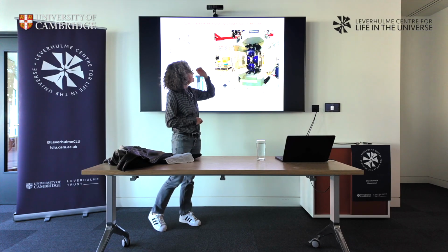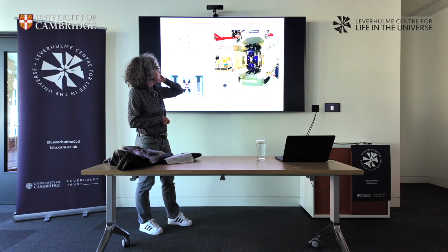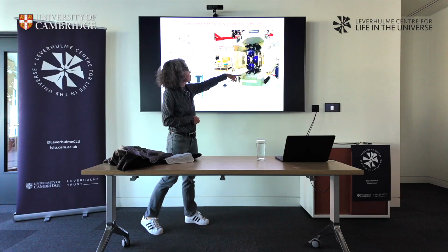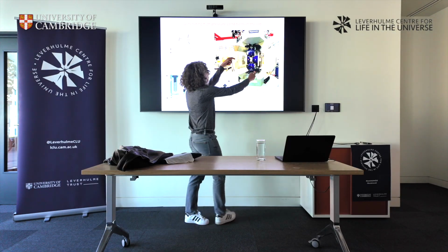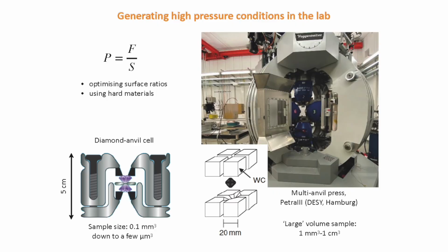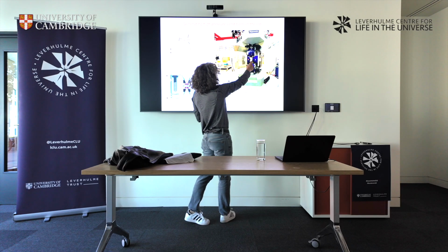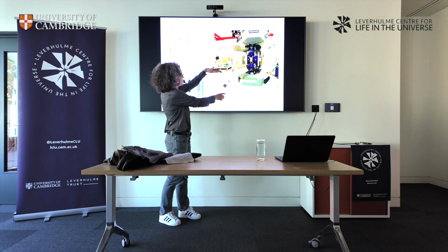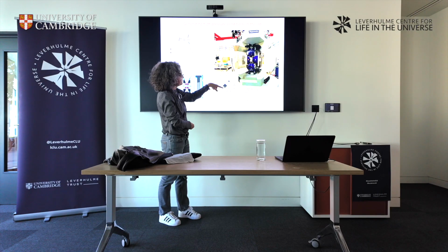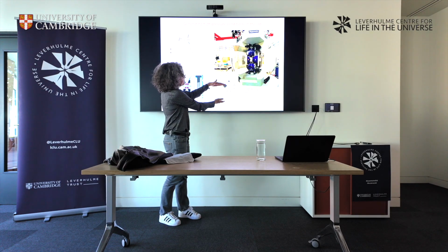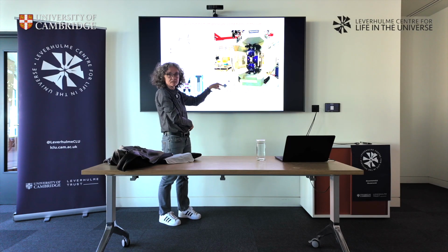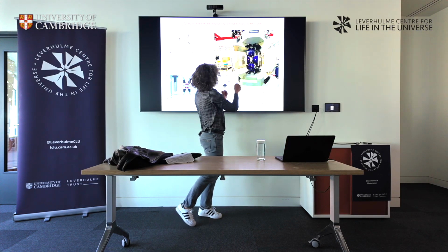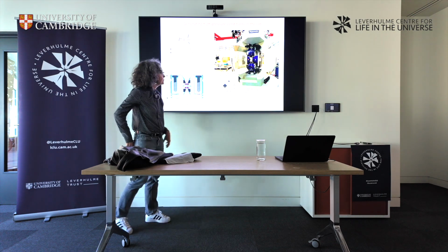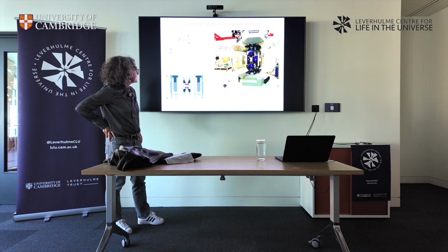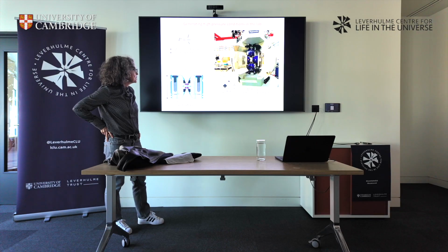This one is a multi-anvil based at the German synchrotron in Hamburg. You have a big press with hydraulic oil. You have this first stage of anvils here, 6 anvils. In the cube in between, you put 8 other cubes that are truncated, and in the middle, you put your cell assembly. Basically, every time you have a nice surface ratio, and at the end you have a huge surface here and a very small one in contact with your sample. You can reproduce high P-T conditions.